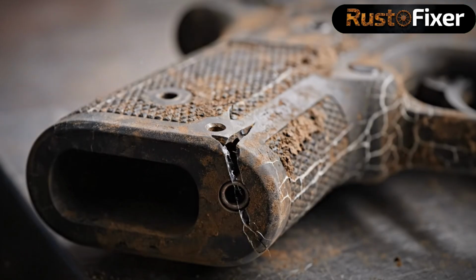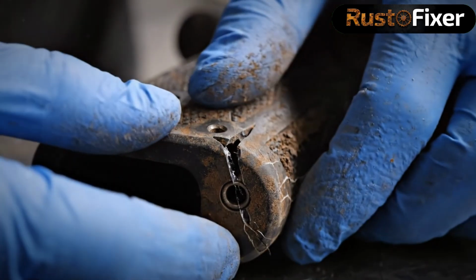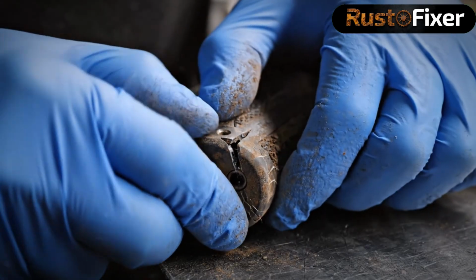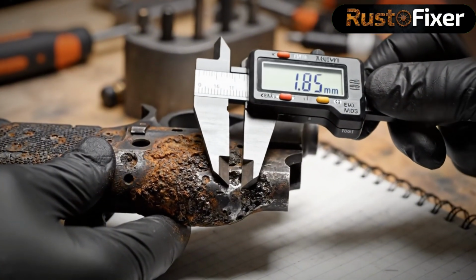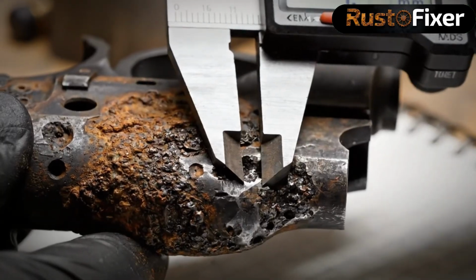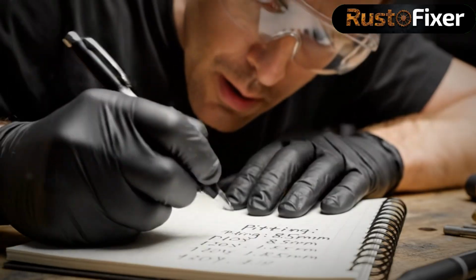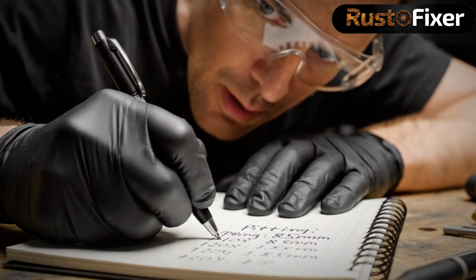The polymer frame, once robust, is brittle and discolored. Stress cracks are visible around critical areas. Digital calipers are used to measure the slide's thickness in critical areas. The readings are alarming, significant material loss due to deep pitting.